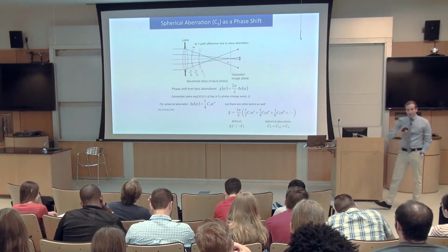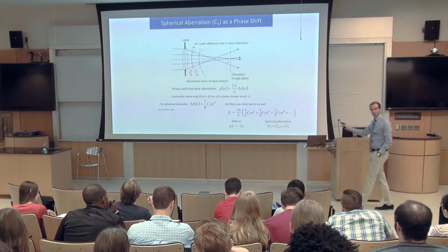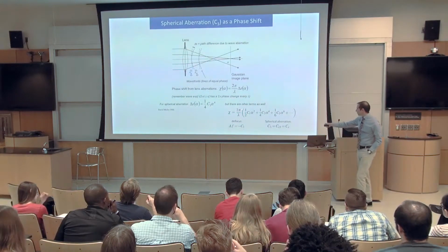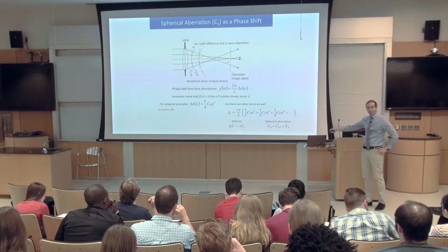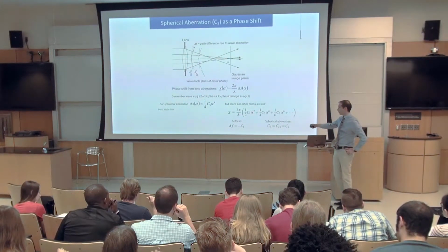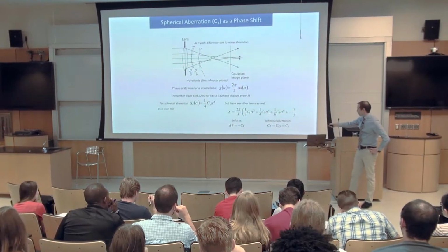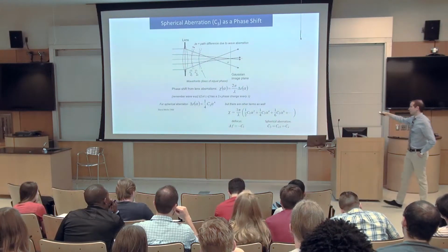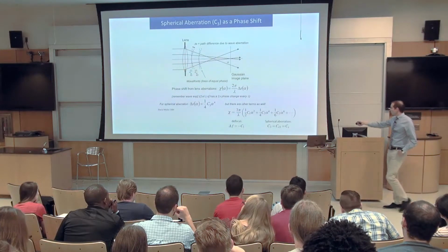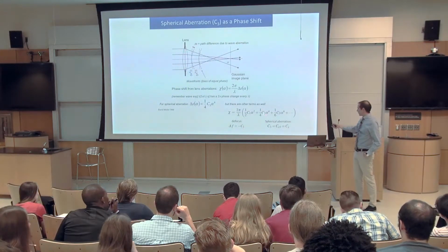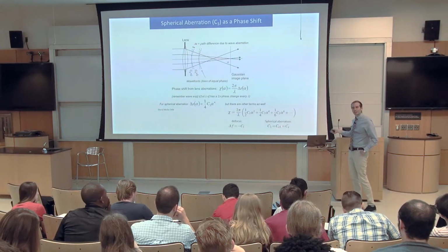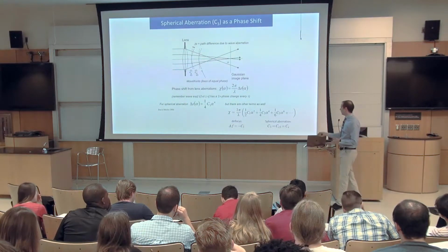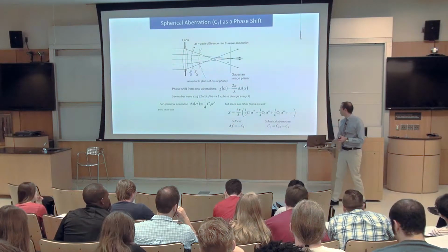What we'll see in the next lecture is that there are many other aberrations. I'm just going to show you a few. We have first order aberration, defocus. So this is C1, which grows as alpha squared. We have spherical aberration, which grows as alpha to the 4th. And then we have higher order aberrations, C5, and so on. You might hear spherical aberration also called C3 or CS. Just to be clear, those are used fairly interchangeably. C1 is usually just called defocus.